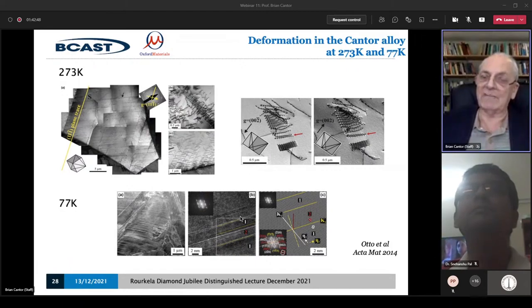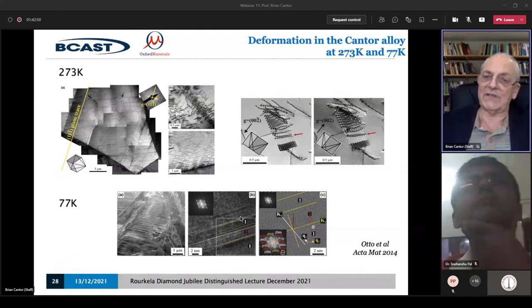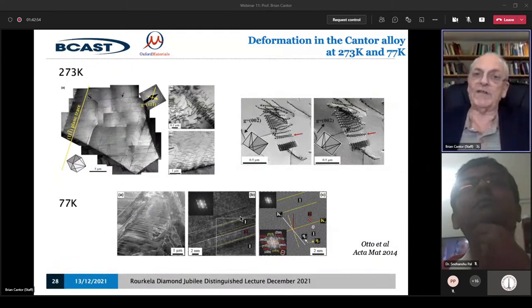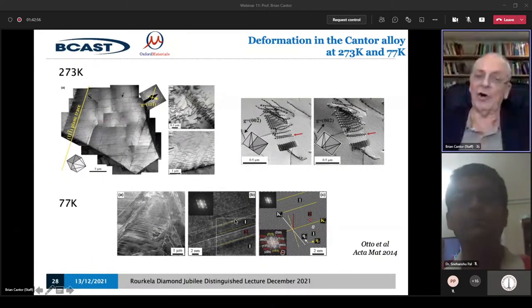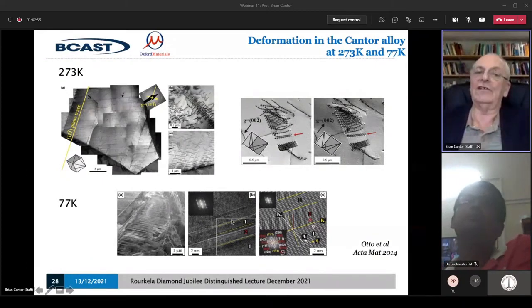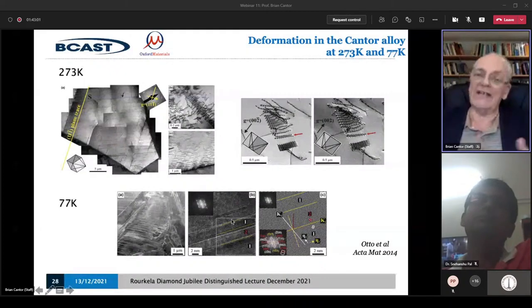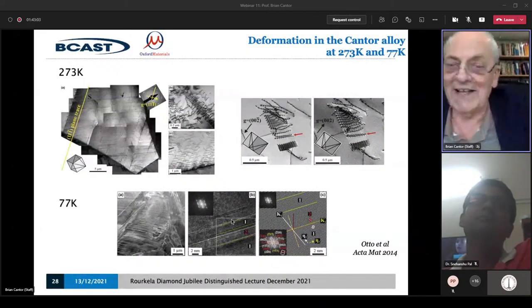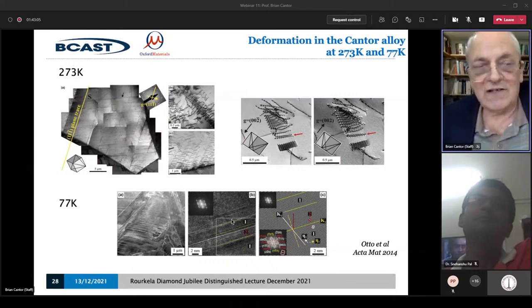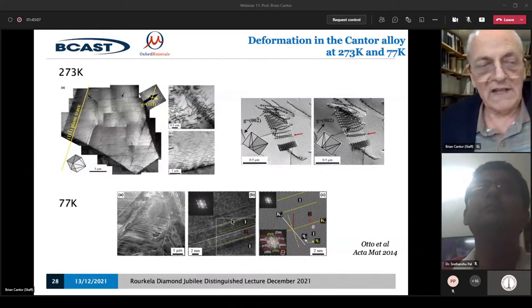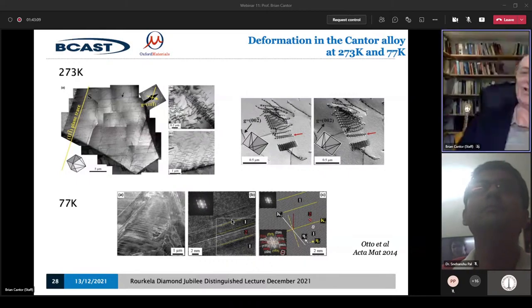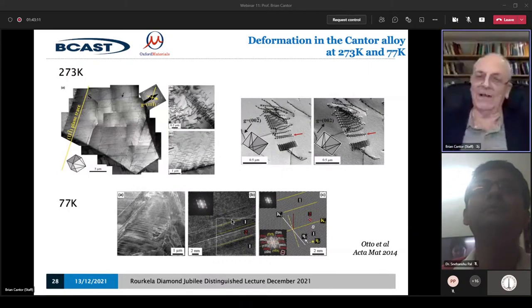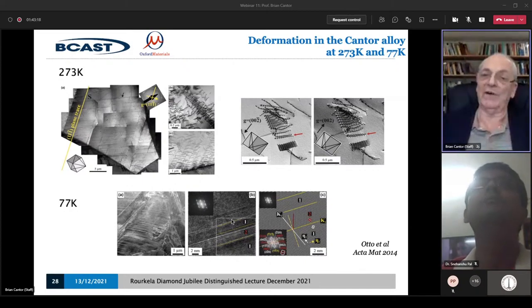Deformation can take place by regions of the material moving from FCC to HCP. The twinning happens. The movement from FCC to HCP all happens because the stacking fault energy is low. So if you tailor it, and people have done precisely that, they have made what are called TRIP and TWIP, T-R-I-P and T-W-I-P, multi-component materials by tailoring the stacking fault energy.